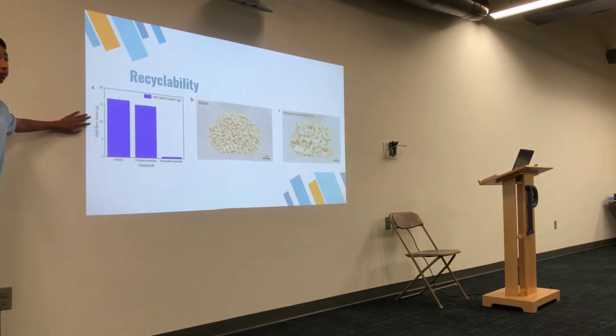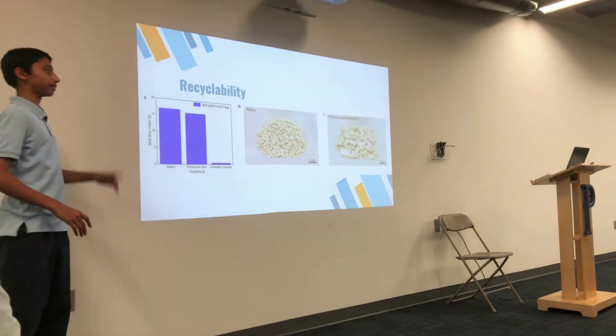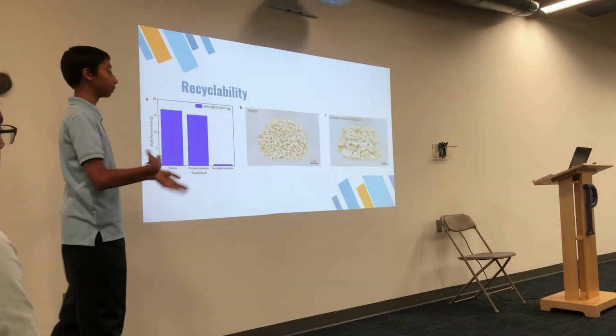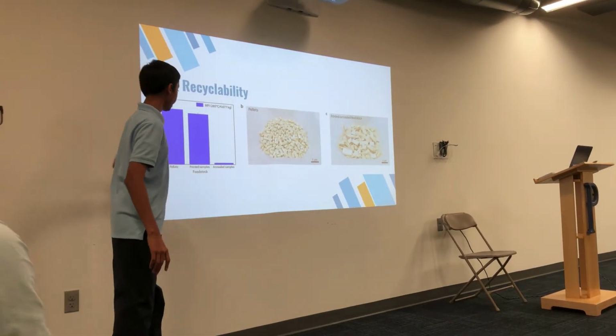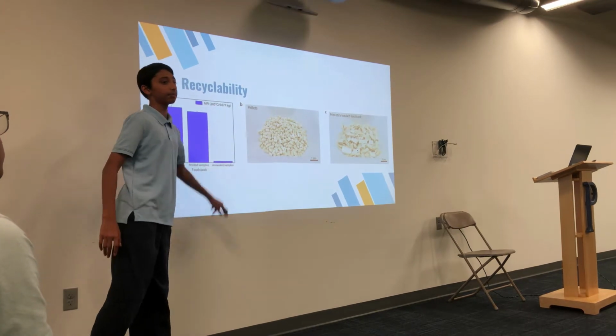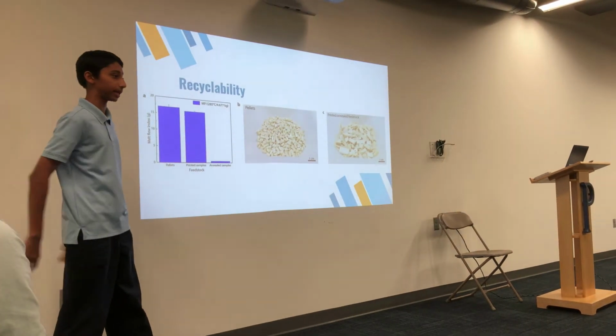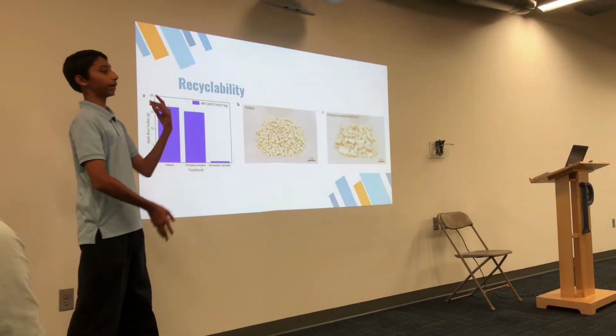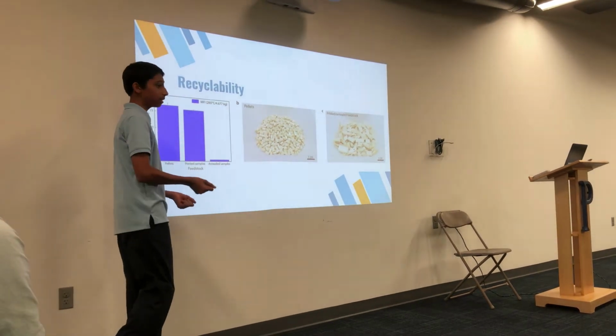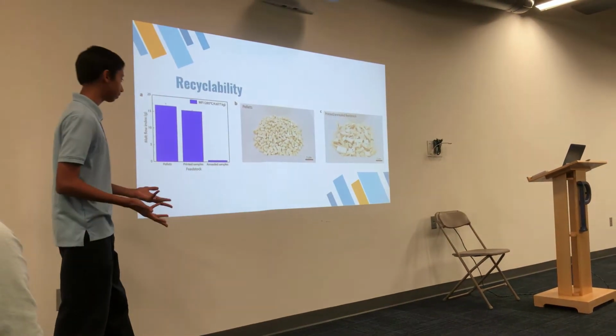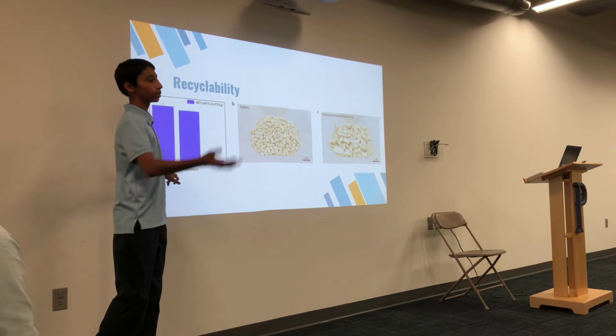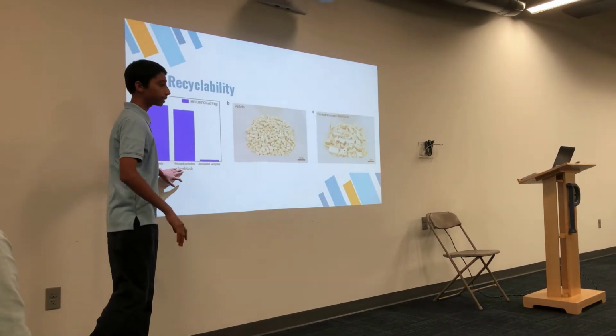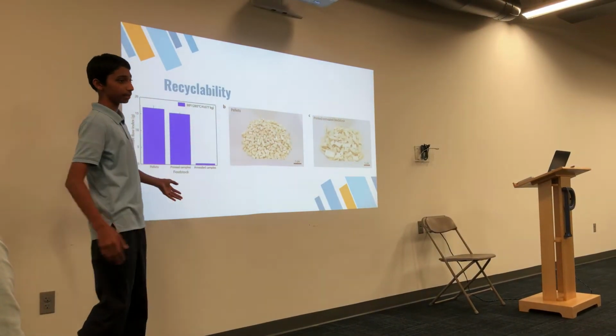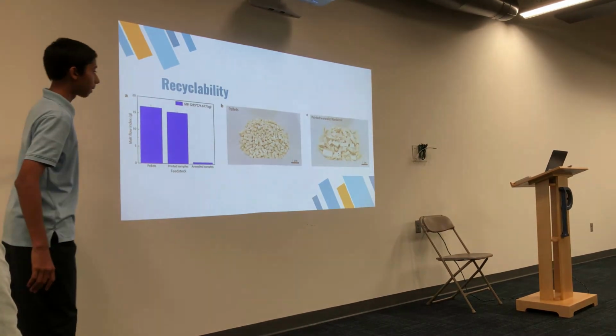And the higher the melt flow index, the less viscous the material is, so the more fluid. Knowing that, this means that the annealed samples are very thick. If you try to melt it down, you can melt it, but it'll be very thick and syrupy and gooey, and it won't be easy to recycle. Whereas the pellets, which is what you buy from the store, and the printed feedstock, which is printed but not annealed, are much more fluid.